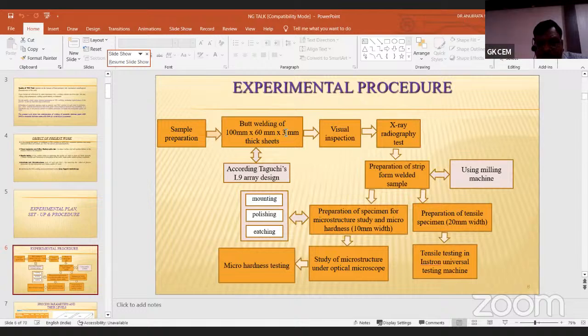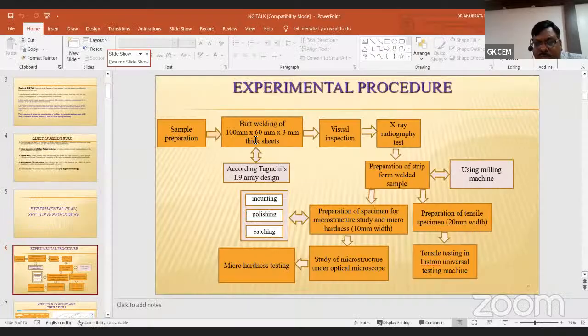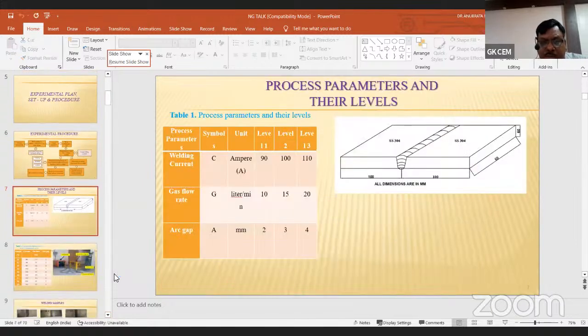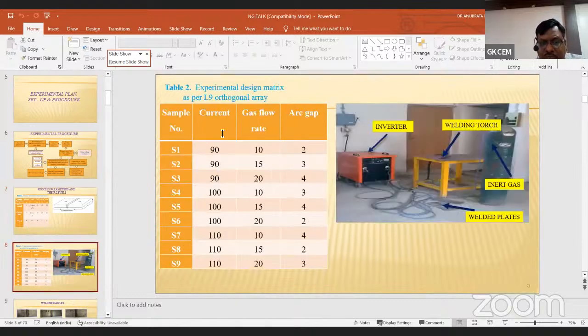In this experimental plan, we perform a butt weld of 100 mm by 60 mm by 3 mm thick sheet by using the TIG process. After that, visual inspection and X-ray radiography have been carried out. A small cutout strip has been taken from the welded sample to prepare a microstructure specimen, a tensile test specimen, and a hardness specimen, and finally we get the respective strength of the particular weld by testing it in an Instron universal testing machine. These are the parameters: current, gas flow rate, arc gap. This is the experimental setup.